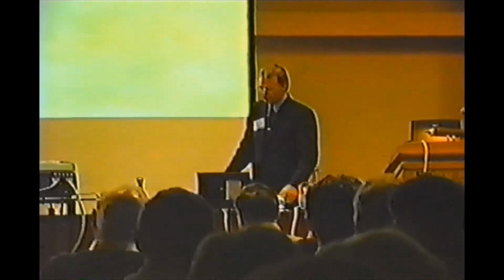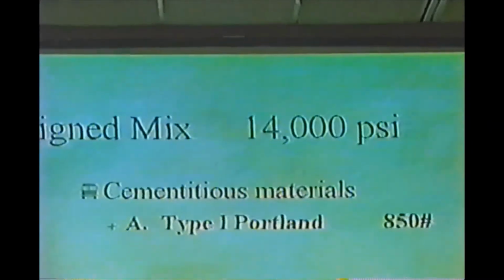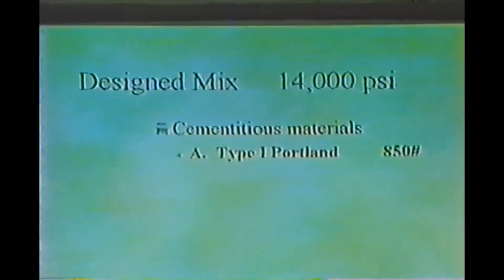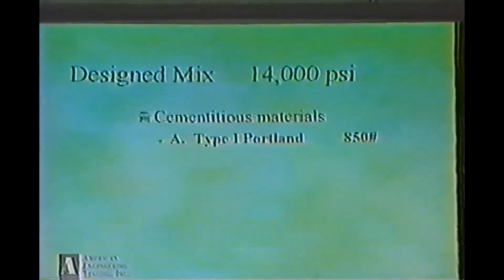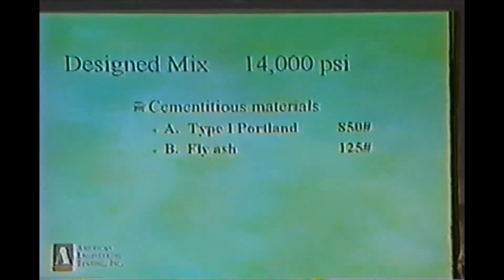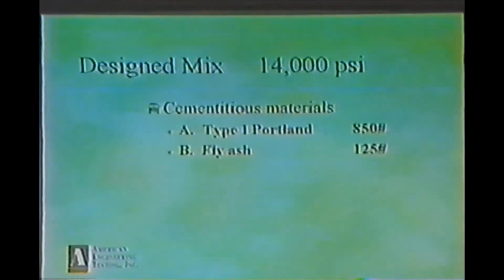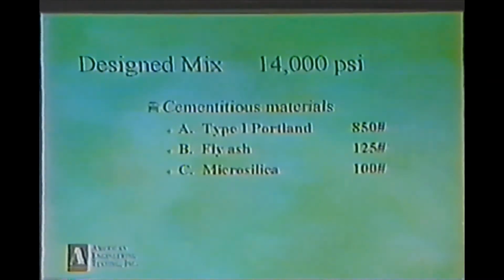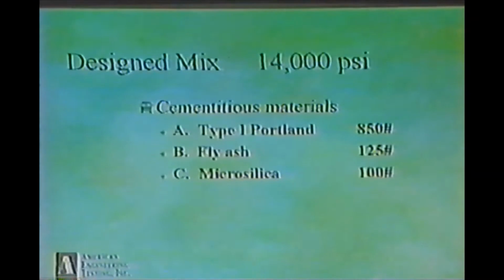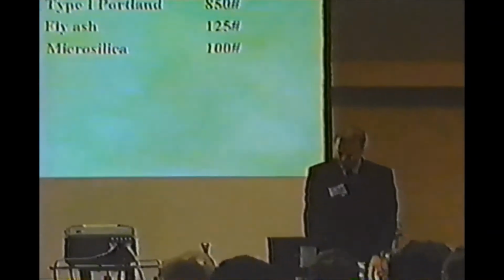What does it take to develop 14,000 pound concrete? The design mix, cementitious materials. First component is type 1 Portland, 850 pounds of materials. Fly ash, add 125 pounds to the mix. Microsilica, an additional 100 pounds to the mix. This gives us a total of 1,075 pounds of cementitious material.